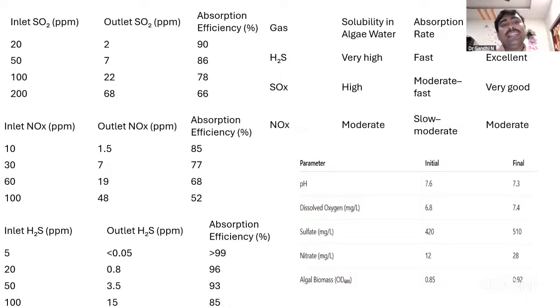So taking that fact into consideration, we have used a lesser concentration of this NOx in the laboratory. And there also we found that the outlet concentration of this NO2 is around 1.5 ppm to 48 ppm, and the percentage of removal is around 52 to 85 percent. That is not a bad removal efficiency, because the organisms which we have taken here also have the capability to reduce this particular NOx.